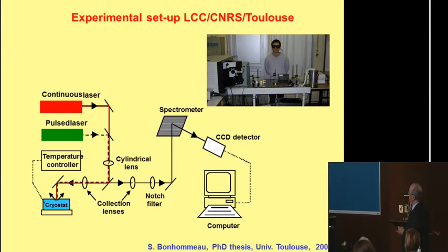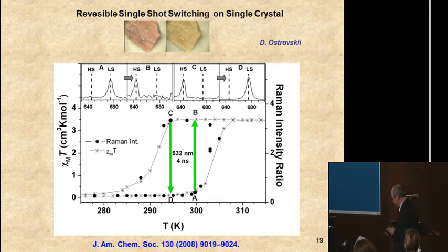So then, if you look now at the experiments, what you can see here, okay, when we are here in the point A, as I told you, we are in the metastable state, low spin state, okay? If you look at the Raman spectroscopy here, low spin state is characterized by one peak, one Raman band here, and nothing in the high spin form.